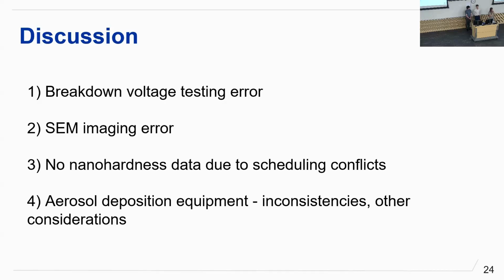For our SEM imaging, we also only cross-sectioned one sample, so there were not a lot of replicates there. For porosity, we only analyzed one cross-section per image, so it wasn't very representative of the whole sample.